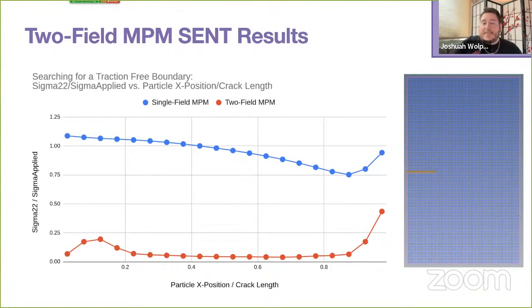So first, let's see how this two-field MPM approach works for the SENT test. And immediately we see an improvement over single-field MPM. Specifically, between 20 and 80% through the crack, we see that the crack is mostly traction-free, save for a bump in the stress concentration factor near the crack opening on the left. And this implies that the opening of the crack is interfering with the overall dynamics of the specimen. And as such, even between 0.2 and 0.8, we still have some residual traction occurring.